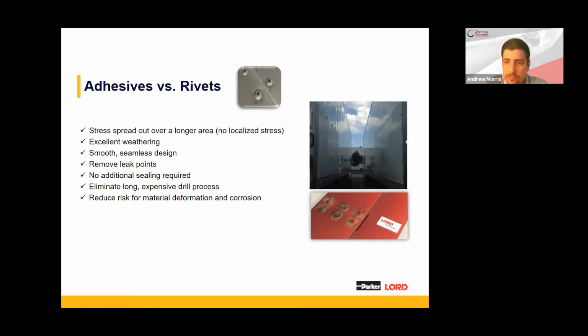Compared to rivets, adhesives distribute the load across the entire area of the joint. So this can increase the overall strength and prevent damage that might otherwise occur under load. As you can see in the photo at the bottom, rivets and mechanical fasteners can present issues with weathering, corrosion, and leaking as opposed to adhesives. So adhesives would eliminate any additional sealing step that would need to be done.